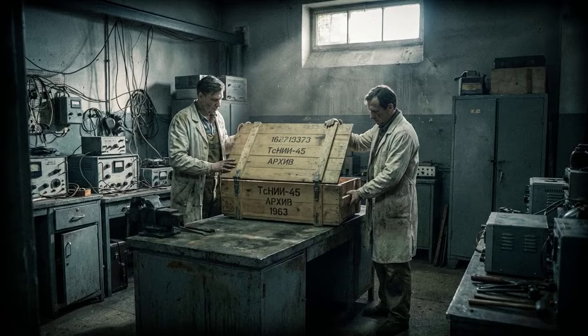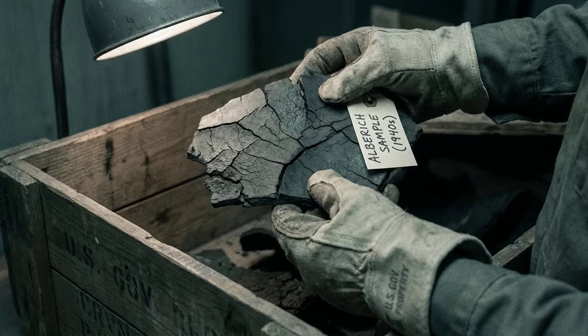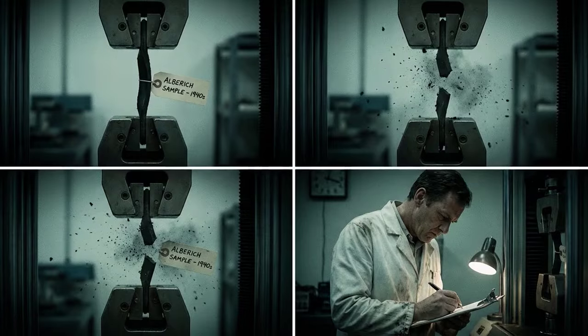The TSNII-45 Materials Laboratory receives a wooden crate from the Moscow Naval Archive. Inside, a rubber tile recovered from German U-boat U-1105, scuttled in 1945 off the Danish coast. The sample spent 18 years in a warehouse, exposed to temperature swings and humidity. The lead engineer lifts the tile with both hands. The rubber surface, once elastic, has hardened and lost flexibility. He clamps one edge in a tensile tester and pulls. The material cracks and crumbles at only 60% of its original rated strength.